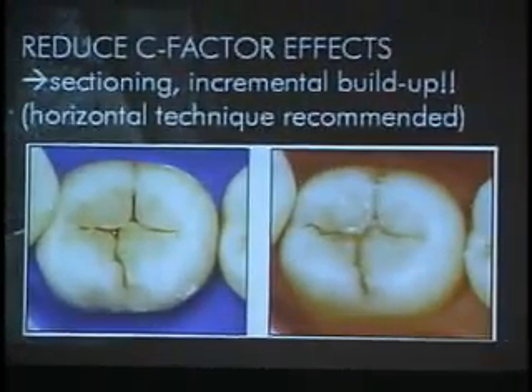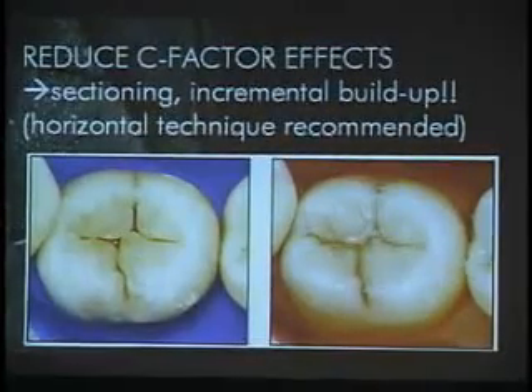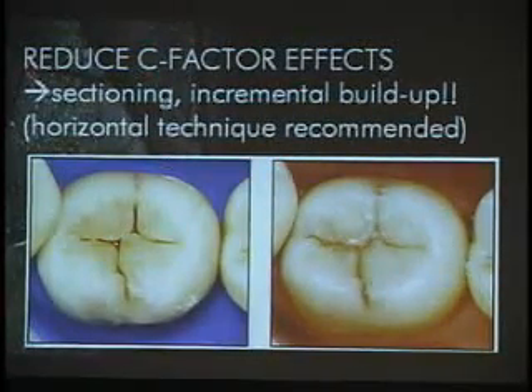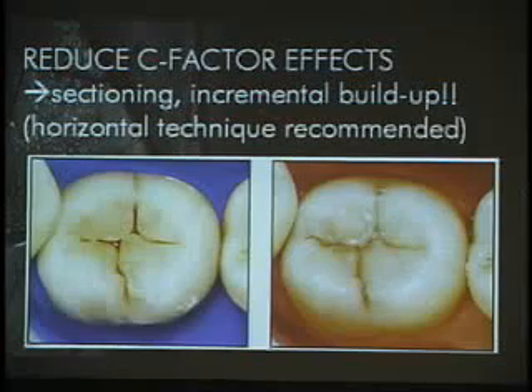What about the placement technique? The placement technique, we know, has been influenced by something called the C factor, which is the ratio between the bonded and unbonded surface of the restoration. And we know that when the C factor increases, we have more problems of stresses. And that's why common sense is telling us that the C factor can be reduced in different ways, and sectioning, incremental buildup is usually agreed by everybody.